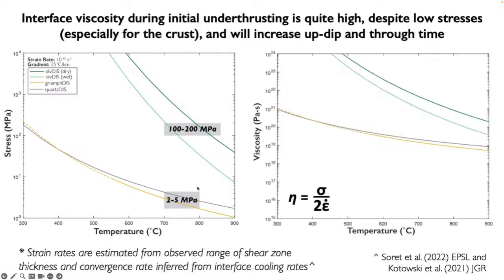Now, the important thing is that we can use these stress estimates now with the calculated strain rates to estimate viscosity. We can do that based on this simple relationship. And the important takeaway now is that even though the stresses are pretty low for the crust and maybe even moderately low for the mantle, the viscosities that those stresses yield are relatively high. And that's because the strain rate is very low.